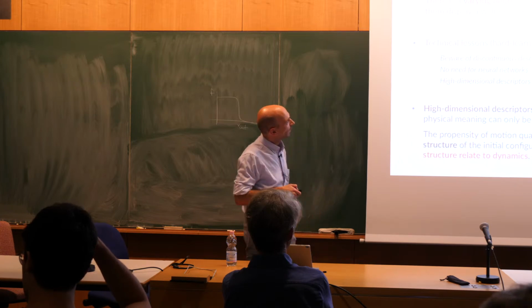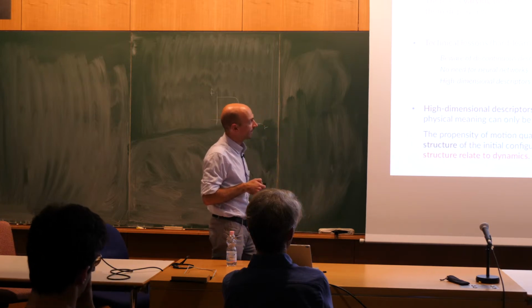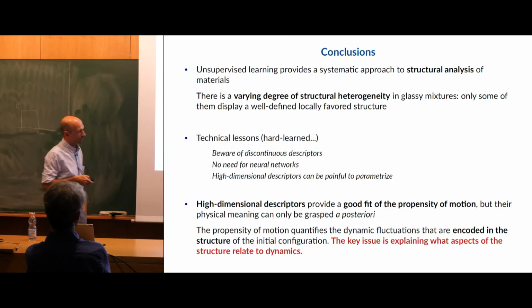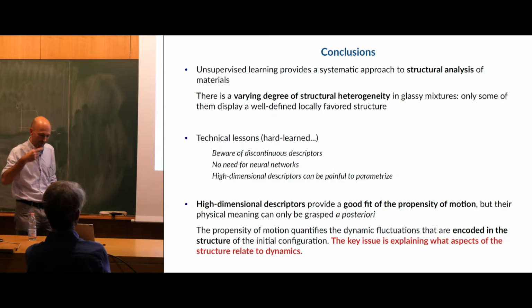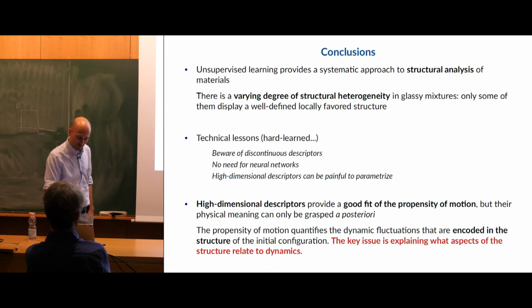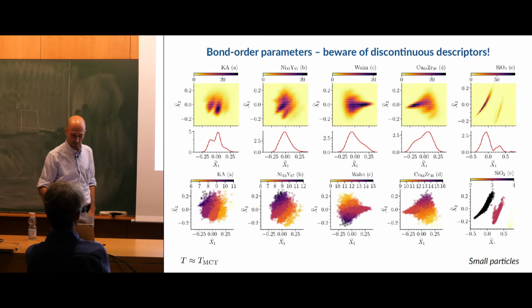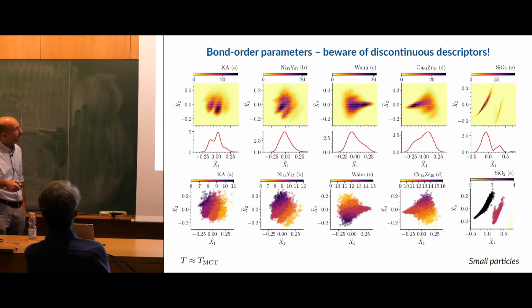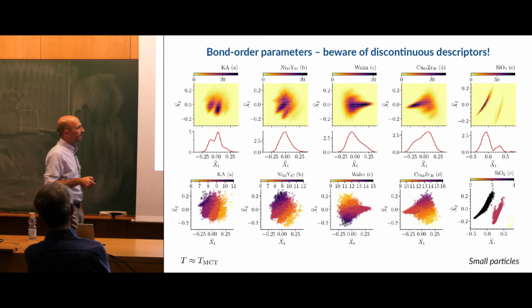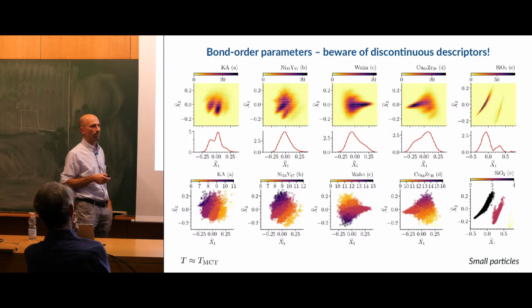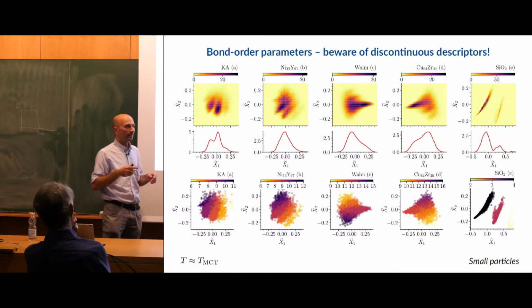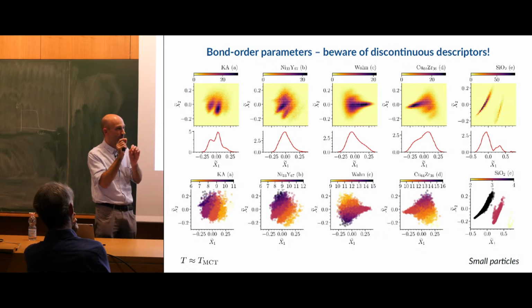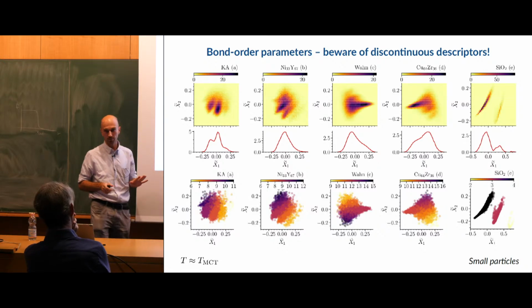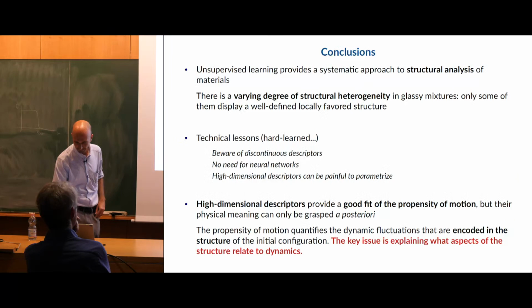Okay? There are a few technical lessons that I've learned the hard way on the way. First of all is beware of discontinuous descriptors. So in the first round of analysis, we used the bare bond order parameters without any smoothing, and this is the kind of pictures that you would get. So essentially, you have this fingering, these bands, that you can easily track down to different coordination numbers. So basically, the algorithm just learns that you have partitioned your environment according to the number of neighbors, and it will find out these slight discontinuities and project them on the first component. So pay attention to that.